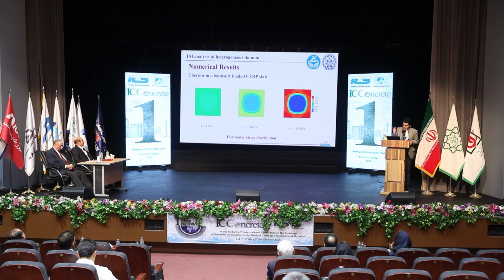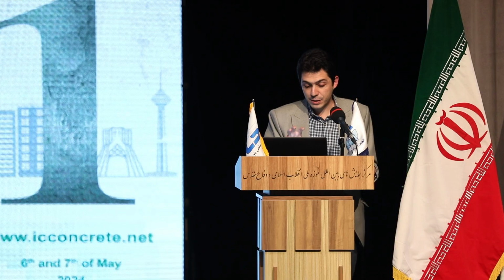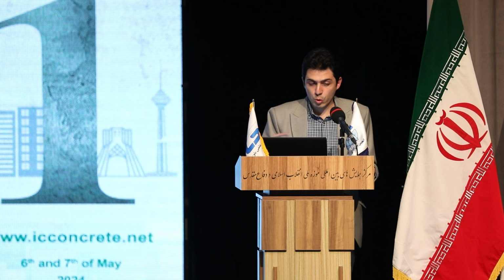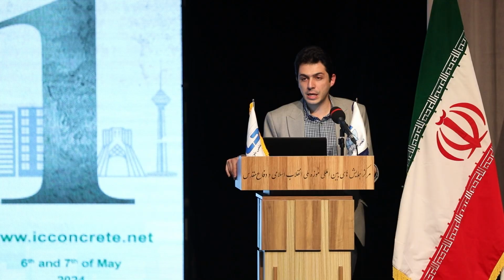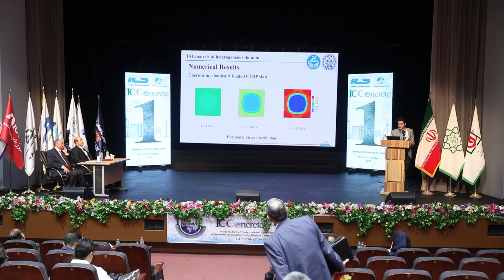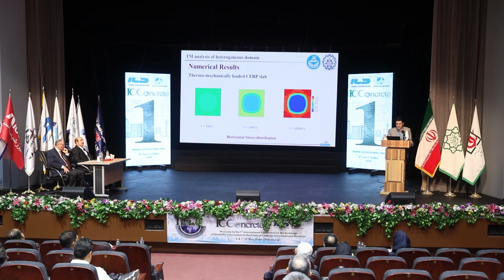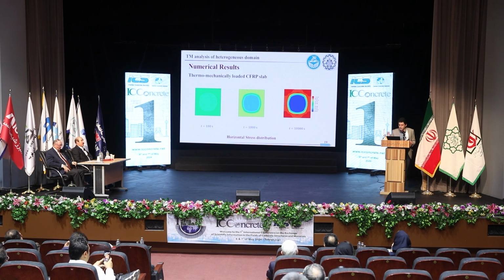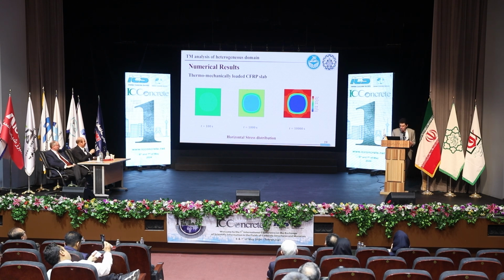The nonlinear behavior of these materials can be completely seen from these figures, which are completely captured by our proposed method. And finally, we have chosen one fiber at the middle of the slab with its surrounding matrix, and we have plotted horizontal stress distribution inside these fibers at different time instants, as you can see. At all time instants, the fibers are in compression while the matrix is completely in tension. The equivalent models, which do not consider any distinction between the fibers and matrix, cannot capture this effect, which is very crucial when we want to capture and detect phenomena like damage, crack propagation, or other failure mechanisms.